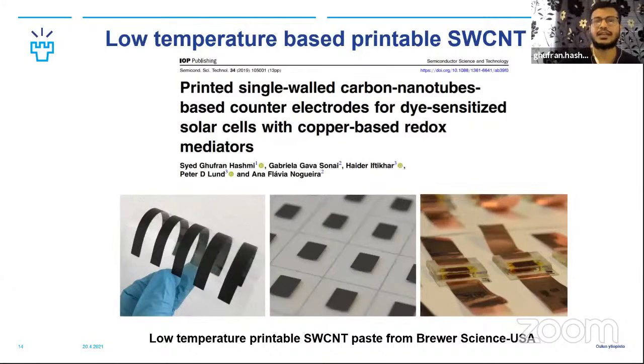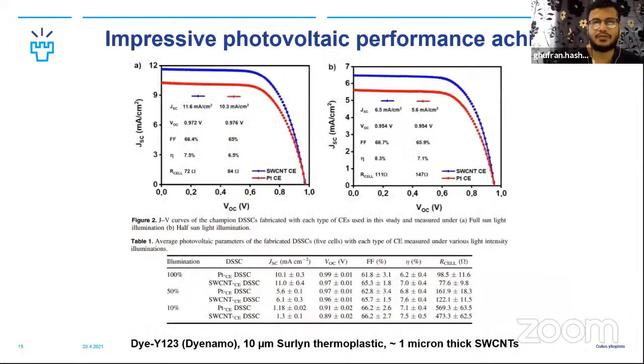So in one article, before my move to the University of Oulu, I tested with my coworkers a low temperature single wall carbon nanotube screen printable paste that you can coat both on glass and also on flexible polymers, as you can see. It was obtainable from Brewer Science, a US company. We tested these devices with copper electrolytes. You can see all the details of the electrolyte composition.